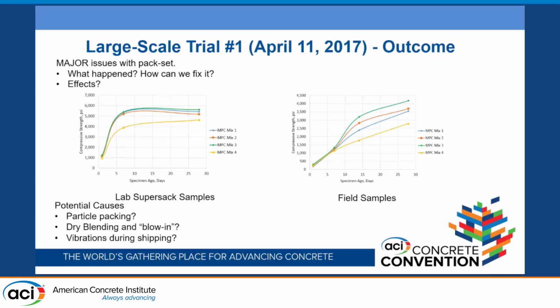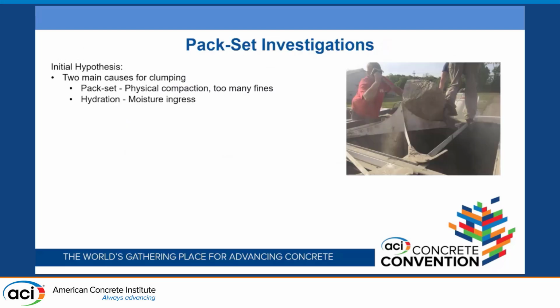And then potential causes: particle packing, dry blending. The way they load the super sacks is they blow it in with an airline hose, or it could be due to vibrations during shipping. And so, two main causes for clumping are physical compaction or hydration, moisture ingress, so physical or chemical. We started out with a physical process.